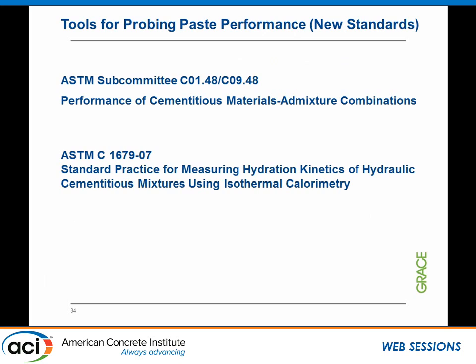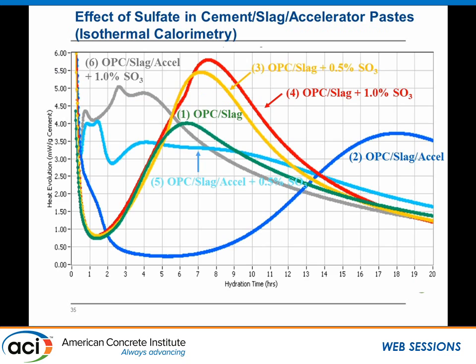And because of this, ASTM already has the calorimetry standard that really is a very, very good tool, in my opinion, when you have something new in your lab and where you have differences in fly ash coming in all the time that could give you differences. This is really a good tool to check. And you would also be using different types of admixtures, that is critical to use. And also a subcommittee to be looking at this combination.